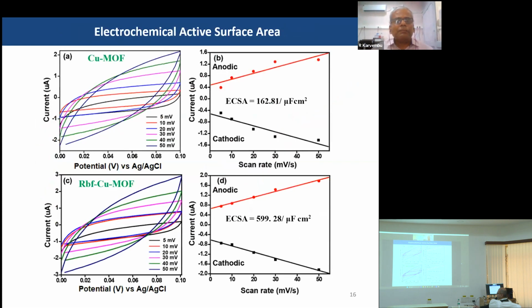We also analyzed the electrochemically active surface area from cyclic voltammograms run in the non-Faradaic region, and calculated the electrochemical double layer capacitance. For riboflavin modified copper MOF, the capacitance is around 600 microfarad per centimeter square, but when we used copper MOF as a catalyst, the capacitance was around 160 microfarad per centimeter square. This is close to a fourfold increase in capacitance when the modified copper MOF was used as an electrocatalyst. This indicates that more ions can be absorbed onto the electrode surface when the riboflavin modified electrocatalyst was used, which might facilitate more reduction of carbon dioxide.